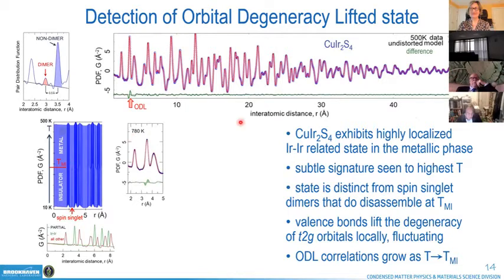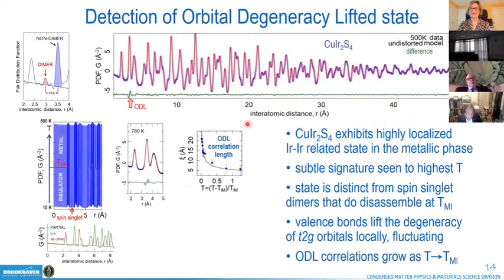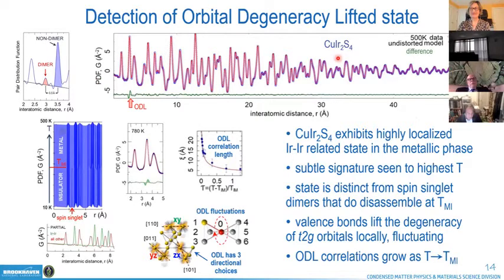If you interrogate the difference curve as a function of temperature, you can estimate the correlation length of this effect, and you can see that the correlation is pretty much temperature independent, and it grows dramatically, exponentially, as you approach the metal insulator transition from above. So if this is a real effect, we have basically discovered something that relates to the pairs of iridiums that is not long range ordered. And we can understand that because each iridium has 6 neighbors, and it has 3 different directions in which this state, whatever it is, can be formed. And thereby it can, through spatial temporal fluctuations, average to cubic.